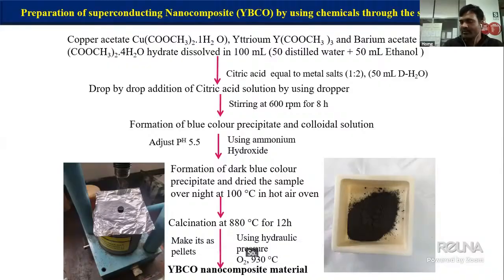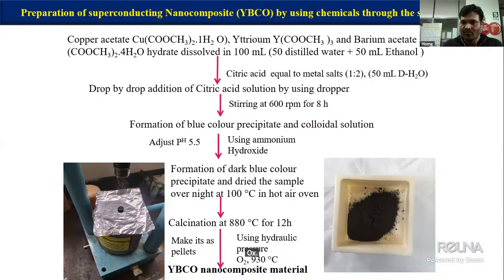Then ultimately it is going to be calcined at a higher temperature, and it will form the powder material. The powder material is going to be reoxygenated in the presence of oxygen. For the reoxidation, we make the pellet. The pellet is calcined again in the presence of oxygen. Then it will form the YBCO superconducting material, which is confirmed here.